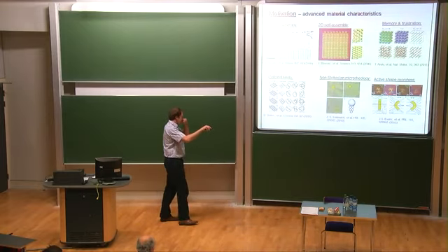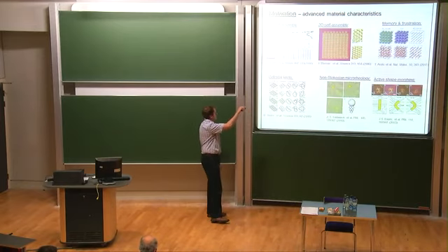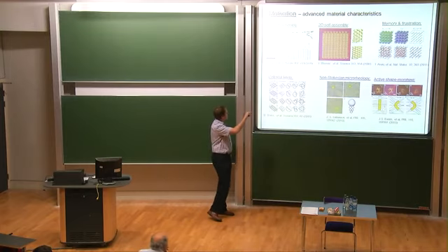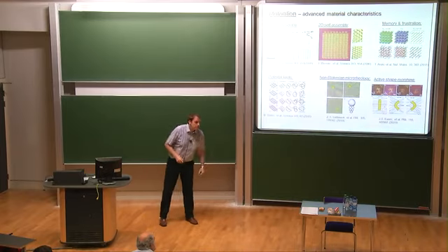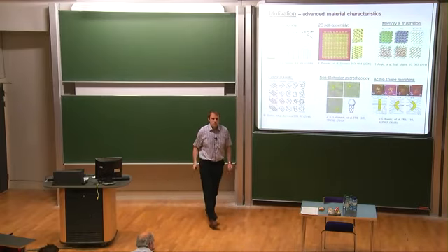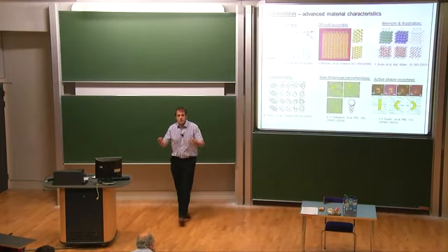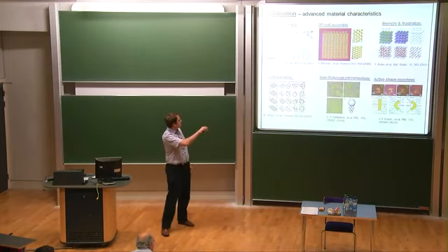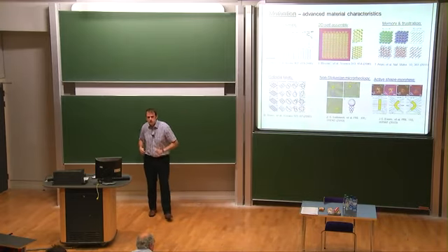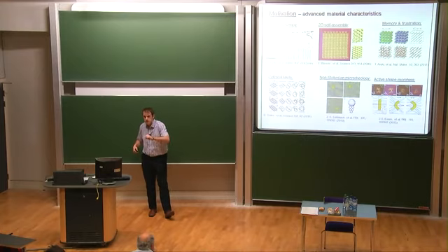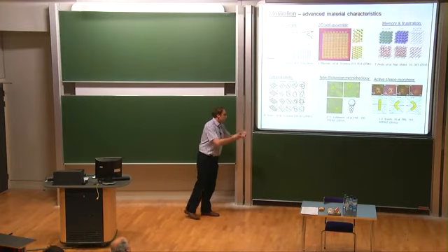Okay, this is also a result from 2 years back. Okay, so I hope you see this. Okay, here again, we are looking at colloidal particles, and I hope you can see these darkish lines going around the particles. Okay, so these are disclination lines, defect lines. Those who know more, it's -1/2 disclination lines. And actually, what we show in this paper here is that we can tie arbitrary knots. Okay, by taking an array of particles, we can tie arbitrary knots. And actually, what we want to say a little bit further, so you tell us the knot, and we can make it. Okay, so we can actually go the reverse direction, not just see what we got.